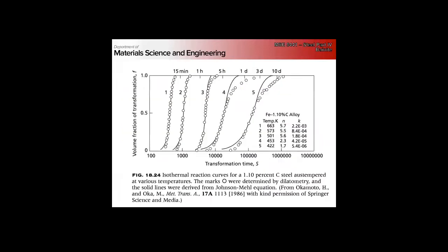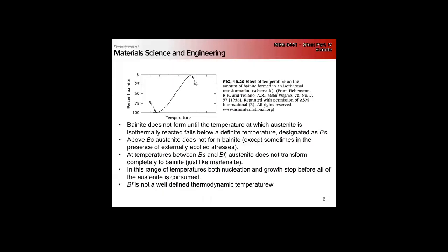And that time is a strong function of temperature. And it doesn't necessarily go to completion, right? We have a bainite start temperature at which the reaction begins. And depending on the temperature that we hold at, we may not go completely to finish.